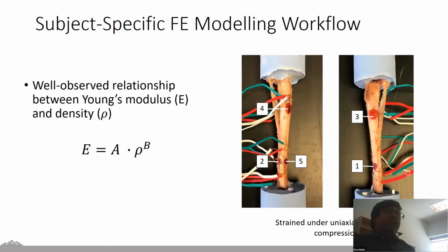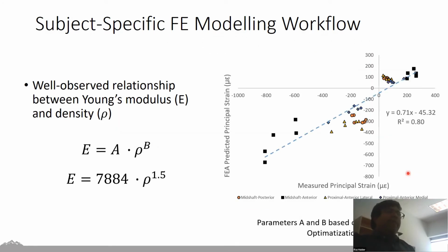Specifically, we took a few of our tibia and put strain gauges onto them and measured strains during loading. We then used Nelder-Mead optimization in order to find the parameters A and B that maximize the agreement between the finite element model and the measurement that we took. And as a result, we got an equation that looks something like this. And we were rather pleased with where we ended up because the exponent that we got made a lot of sense. An exponent of 1.5 is very much within the range of what's been reported in other bone in the literature. And overall, this relationship seemed to yield Young's moduli of bone that made sense when we put in approximate densities of cortical rabbit bone. So in general, this seemed like a really good starting point for this study.